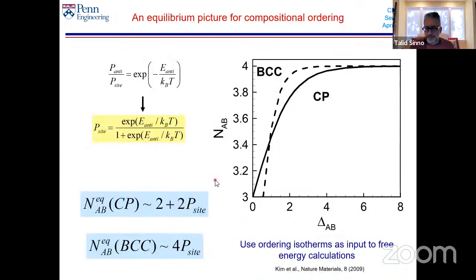So now from this, and you can ignore all of these equations, this is just like an isotherm. This is the cost of the antisite. Okay, all of these units are always in kTs. So this is kT, 4 kT, 6 kT, and so on. And this is, you can think of this as an order parameter where 4 is perfect and 3 is random. Okay, so this is a lot of antisites. This is no antisites. And you can see that the isotherm for the BCC case quickly reaches perfect ordering as the cost of the antisite goes up. Whereas in the close-packed case, you have a lot more tolerance to defects based on a given antisite energy.